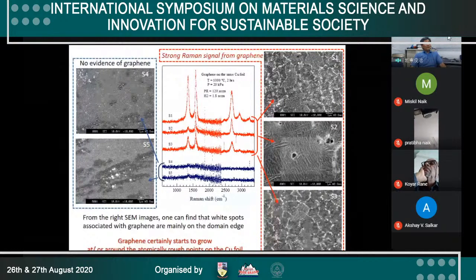So the graphene certainly starts to grow at or around atomically rough points on the copper foil. So making a flat surface is not good for growing graphene. Maybe this is directly related to the reproducibility of growing graphene on the copper foil. Okay, next slide, please.